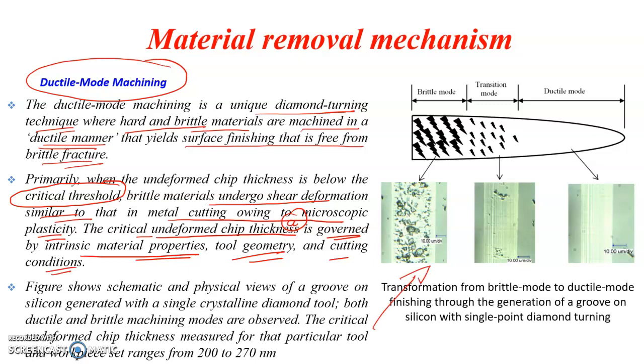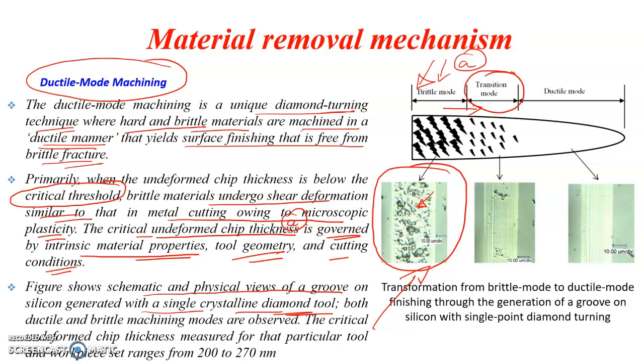And this figure shows the schematic and physical views of a groove on silicon generated with a single crystalline diamond tool. Here the experiment has been done with different values of A. Here the A value is higher than the critical value, so in the cutting we can see the portions having brittle cracks, which have affected the surface finish. Then we are reducing the value of A, and it is now in transition mode, somewhere near the critical value. So the cracks are reducing, and when it reaches below this critical value for A, the brittle material appears to be machined as a ductile material without any brittle cracks.